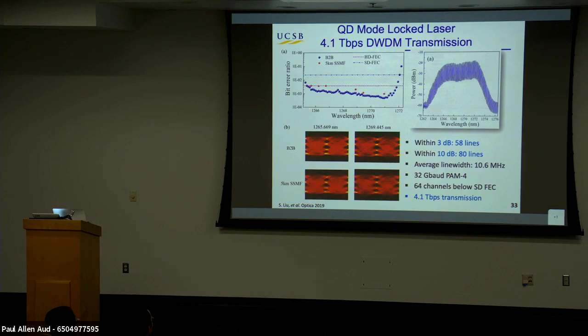So as you go across that, every 20 gigahertz, there's another line here. And each of these circles is the error rate on that channel. And each of them is then carrying PAM4. So when you put that all together, that ends up being about 4 terabits of transmission. So it's a nice way to go beyond where we are today, say 400, 800 gigabit. The HP approach is actually very good for 800 gigabit. This is what to do after that, if you need to get to 1.6 terabit, 3 terabit, or beyond.